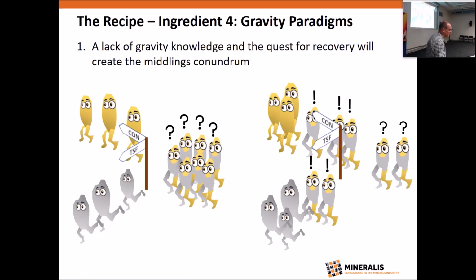So, onto the paradigms. A lack of gravity knowledge and the quest for recovery will create the middlings conundrum. And middlings have a bad habit of building up in any circuits, as we know, but often gravity equipment has no way of relieving that build-up until there's such a mass of it in the feed, it'll just vomit itself out of the circuit, usually to the tailings. So the process design should consider how they'll not be introduced into the process in the first place. And if they do happen to get in, where they're going to be sent for retreatment before coming back around as suitable to either go to final concentrate or tailings products.